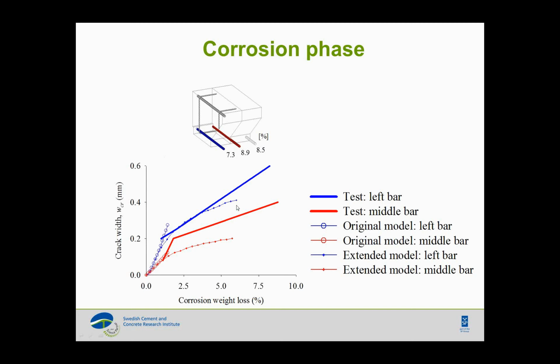But as soon as we move to the extended model, where we account for the rust flowing out through the cracks, then we see this behavior: in the beginning we have crack widths growing very fast, but after a while, allowing for rust to flow out, we have slower crack width growth, and that corresponds well with the experiments. And if we look at the middle bar, we see pretty much the same behavior: in the beginning we have a high rate of crack width development, and then it slows down, and that's what we get in the analysis, where we also include the impact of rust flowing out through the cracks.